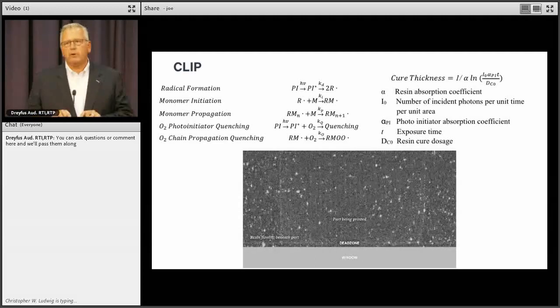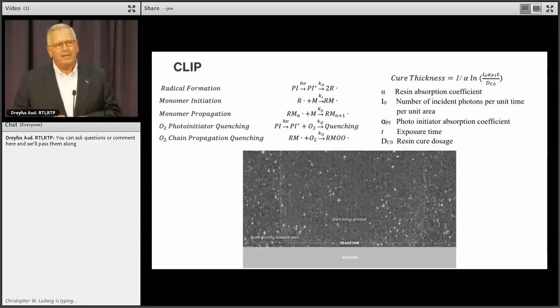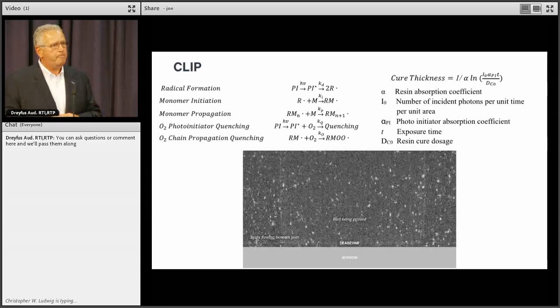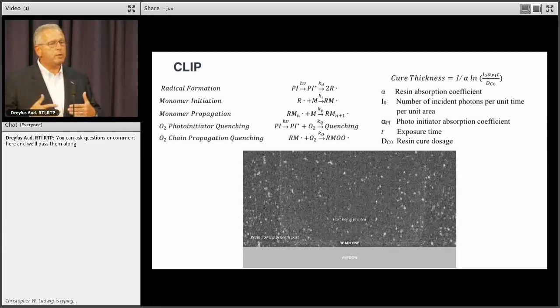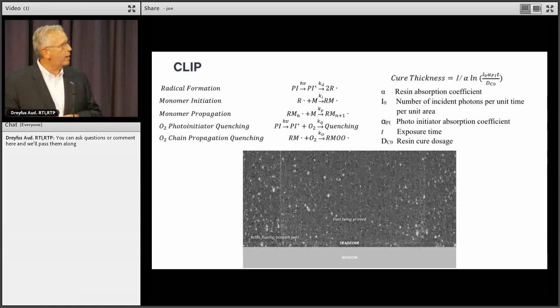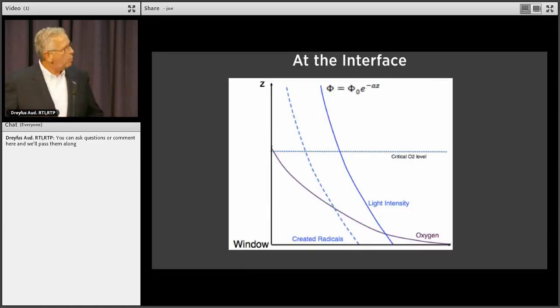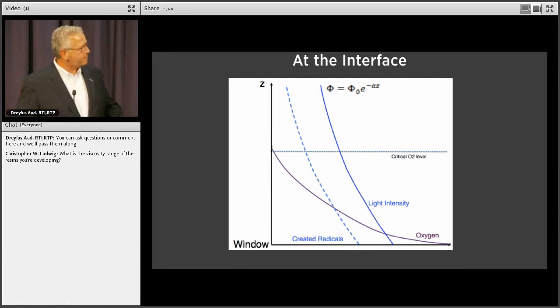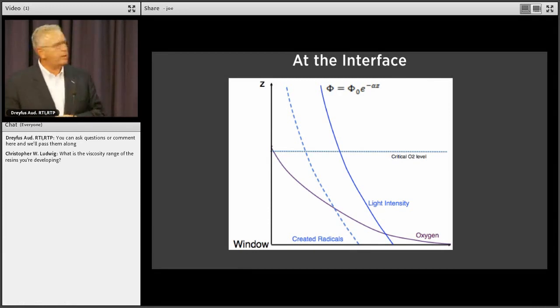And it's a thin river of resin that's able to flow in underneath the part, on the order of about 35 microns thick. It's really tenuous, and we have to control that to a great degree. It's only 35 microns thick. And so when you think about the process itself, this is a plot that we like to look at. This is the z-axis going from the window up into the reservoir. And then you think about concentrations, and you have light in a fairly intense field that generates radicals. And the concentration of radicals tails off as we go further and further into the resin.